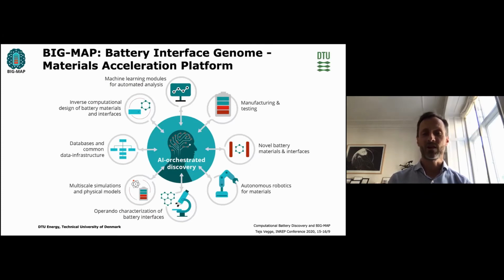If that's not the case, we can automatically launch a supporting simulation that can then identify what is the origin of this phase transition. Is it because we're too high in terms of lithium content? We can then continue the characterization with cell level testing while we launch the second simulation or the second synthesis procedure, such that it is not a sequential process anymore. We can continuously update the materials on the fly.